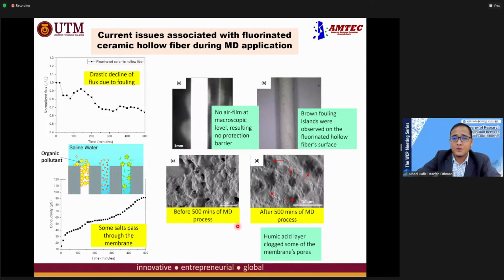Okay? We use the membrane distillation concept, but with this membrane, we can see some decline in the flux. It's because of the membrane. After some time, the pollutant will adhere and settle down on the membrane surface. This can be proved by an autopsy after the operation. So we can see that the pores of the membrane have been blocked by humic acid. Therefore, we would like to further improve the surface of the membrane.